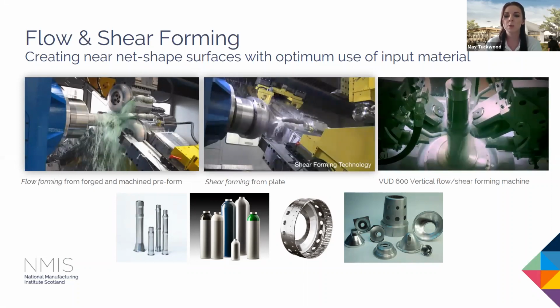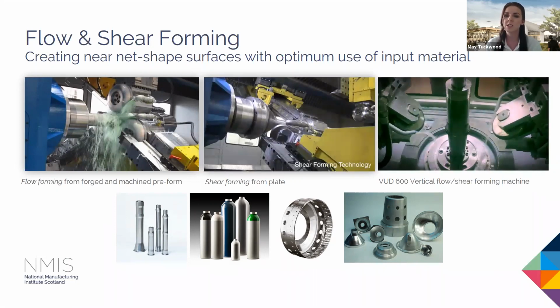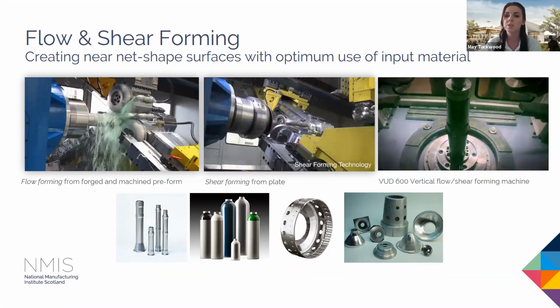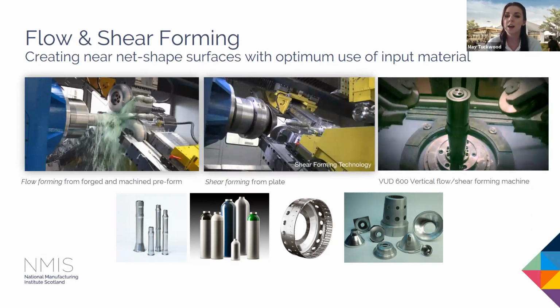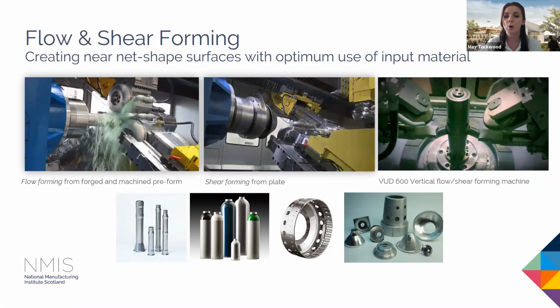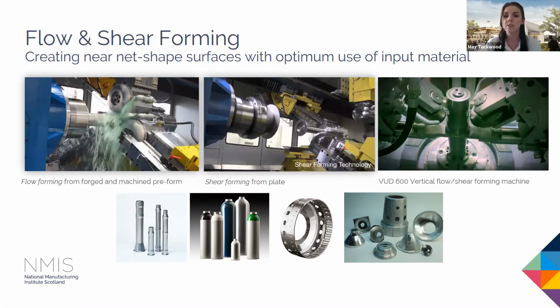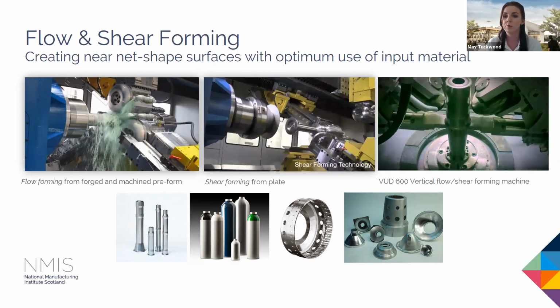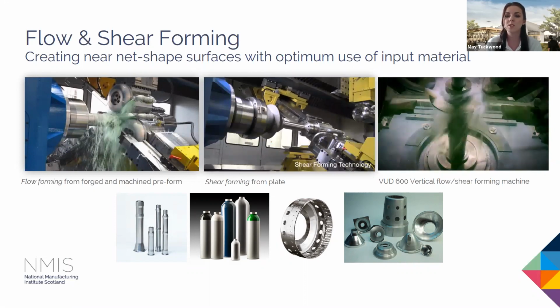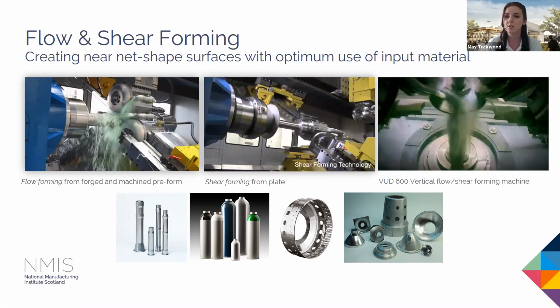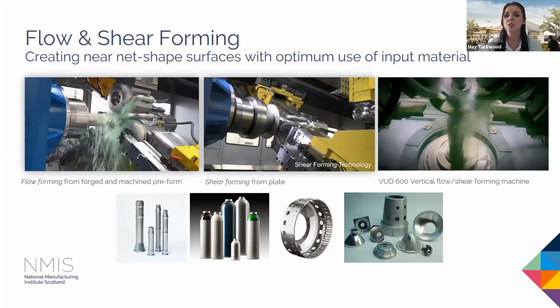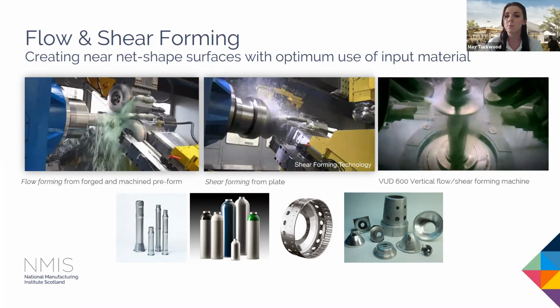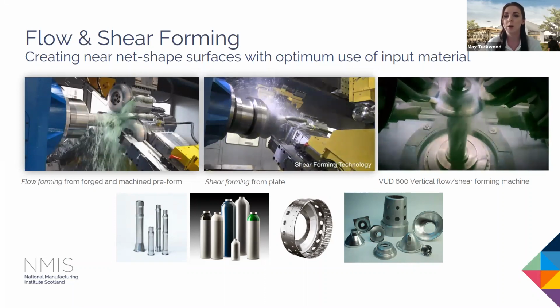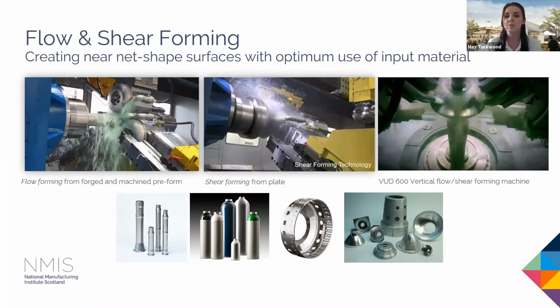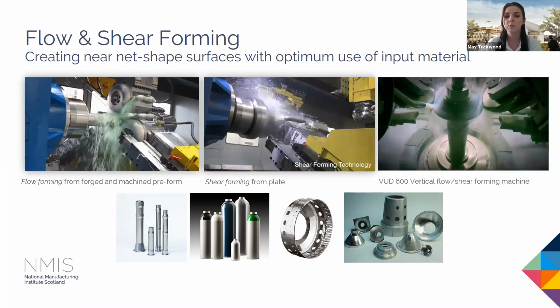So in shear forming, we're starting with plate or sheet material, typically in thicknesses ranging between 3 and 15 millimeters. We have gone as far as 20 in some steel alloys. And we're creating a conical form in shear forming, whereby we're reducing that thickness with respect to the angle that we're forming at. So typically ranging from somewhere around 18 or 20 degrees up to around 60-degree cone angles. Again, these types of components would conventionally be machined from solid, or they would be made from multiple parts where you've got the added effects of welding, heat effects of welding, and final preparation to get to the finished part.